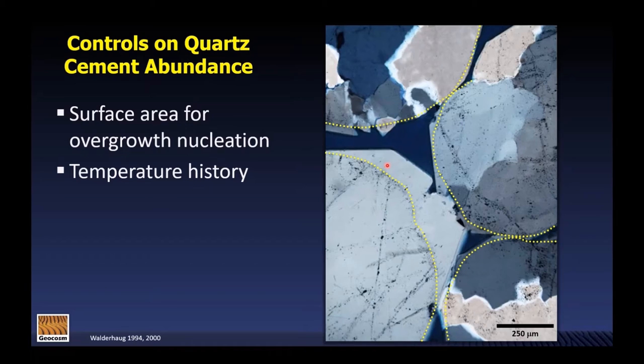Moreover, we know from countless fluid composition analyses of reservoirs that fluid compositions are almost always right at where we expect them to be with respect to saturation with respect to quartz. So he reasoned that the rate of quartz growth will be very slow compared to the rate at which we are supplying silica into the system and then transporting it. And therefore, we have the potential that, at least in many situations, the rate controlling factor in quartz growth will be the rate at which the crystals themselves could grow. And if that's the case, then the two primary things that would control the overall rate of quartz growth in the rock would be the surface area for overgrowth nucleation and the temperature history.